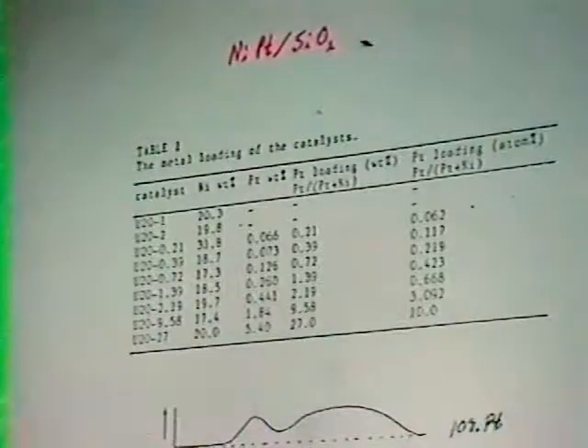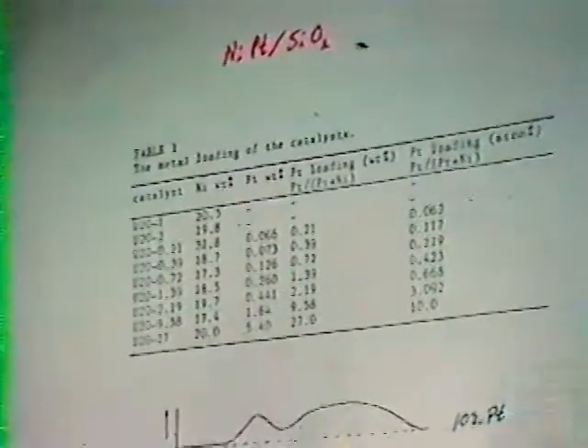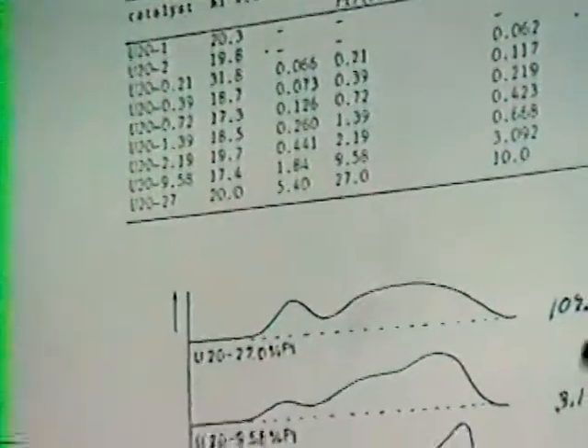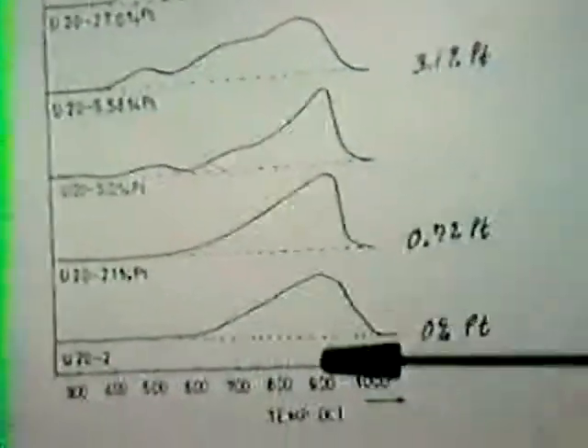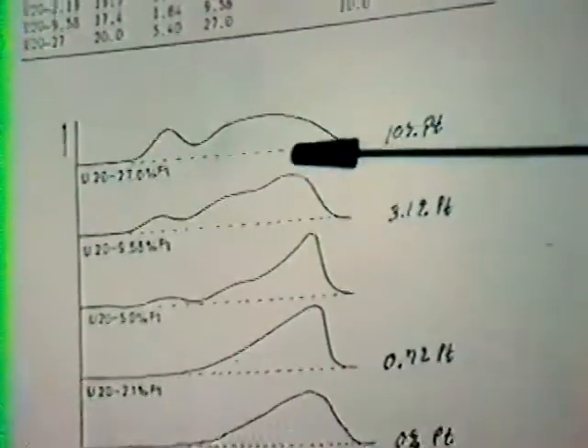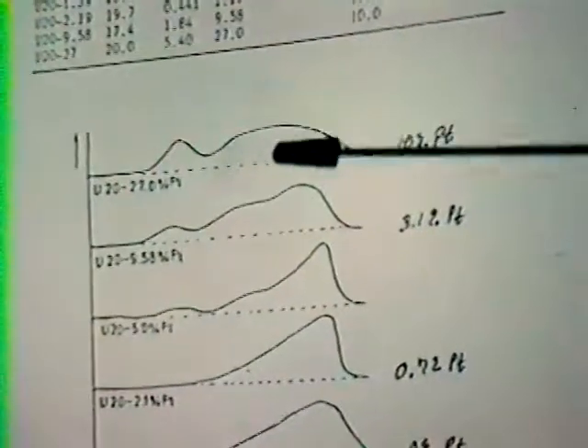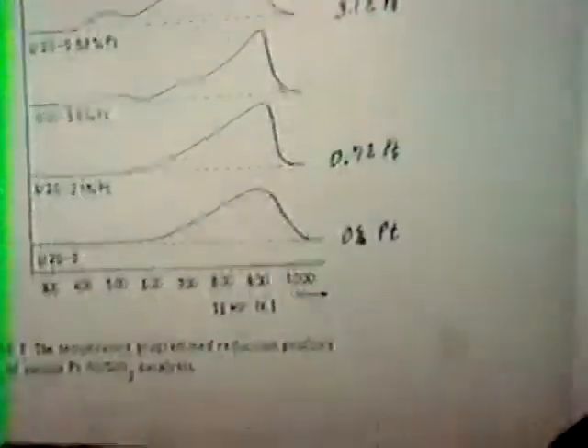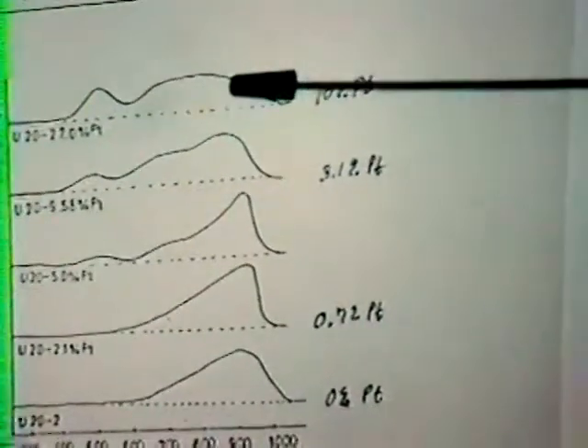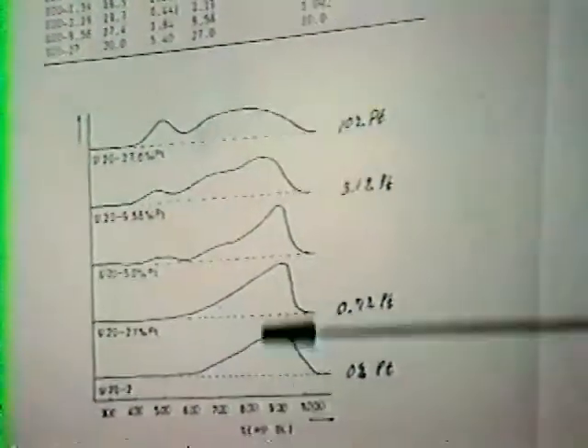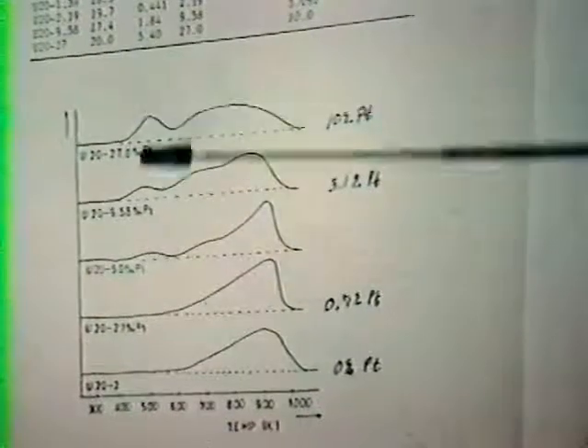and this was for nickel platinum on silica, and among other things they looked at, for about 20% nickel, a system with a little bit of platinum in it, and they saw basically that the reduction temperature, there was perhaps some increase in reducibility, though it wasn't very clear based on the amount of platinum that they were adding. This being obviously nickel, the reduction peak for platinum being somewhere down here, and they were following the reduction of the precursor as opposed to the reduction of the calcined catalyst.